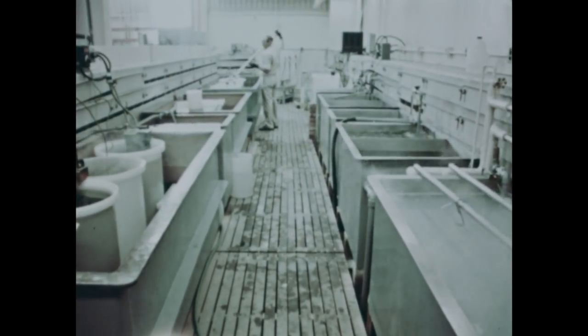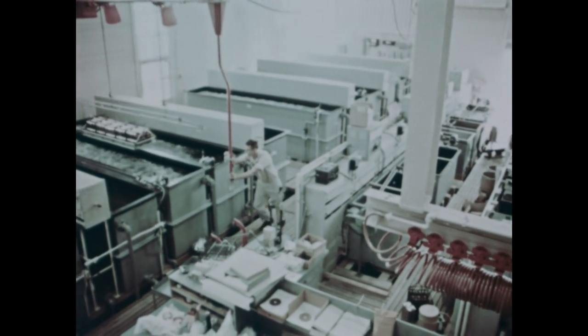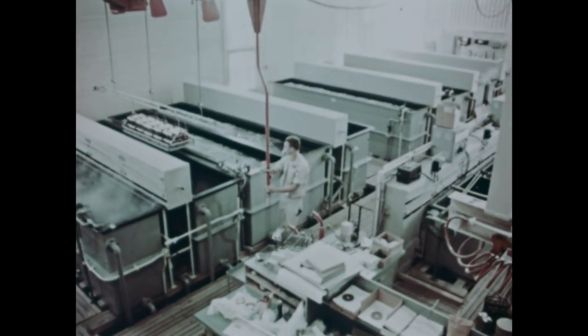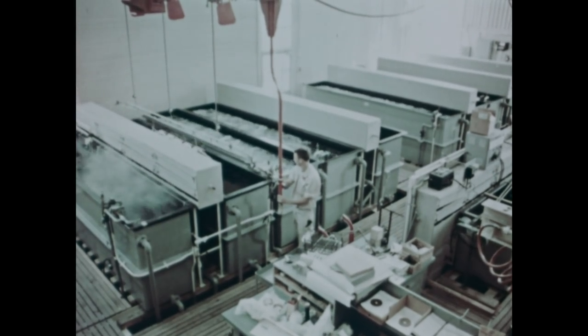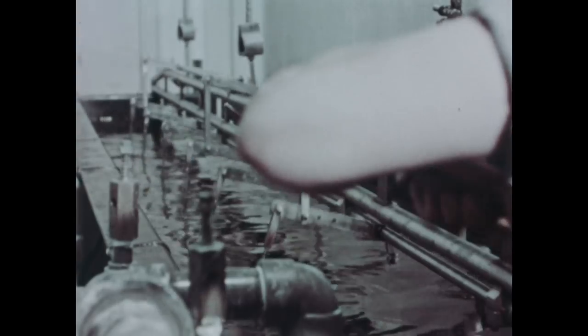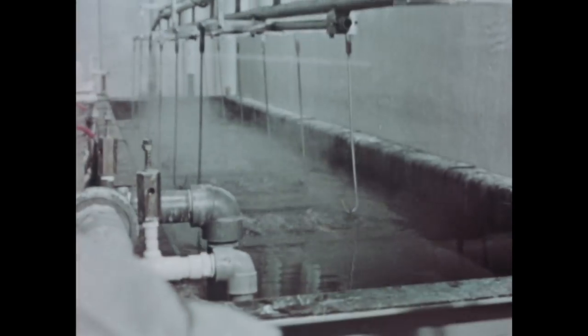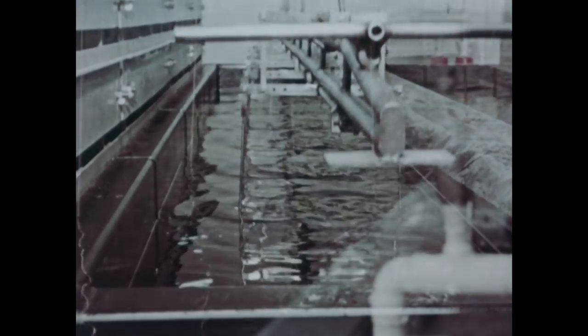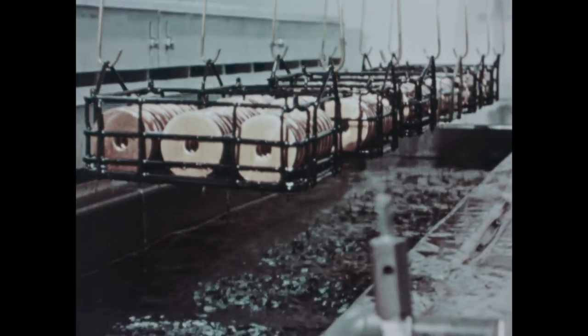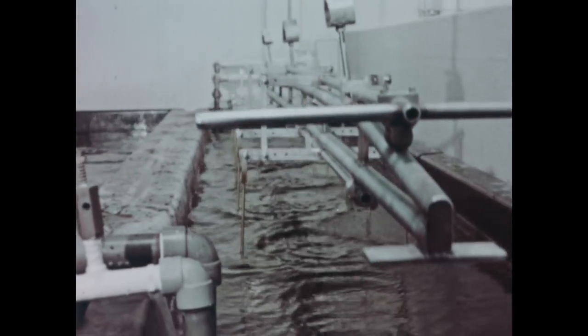Before assembly as well as before annealing, all parts are chemically clean. The cylinders and disks which are to form the ten-foot section are taken through a cycle of twelve chemical and water baths to free them from oxides, oil and other contaminants: water rinse, emulsion cleaner, water rinse, alkaline cleaner, water rinse, bright dip, water rinse.